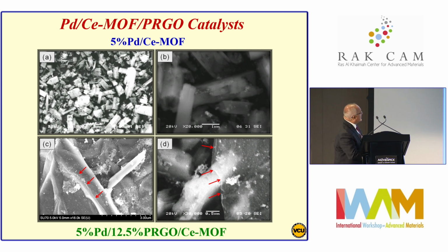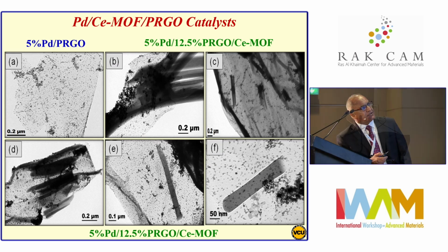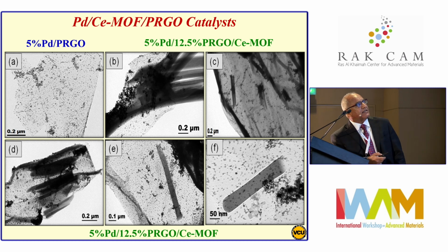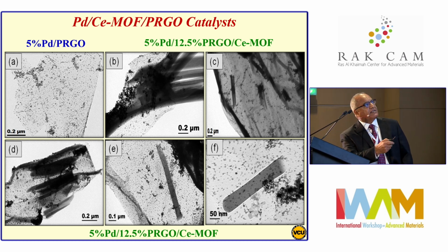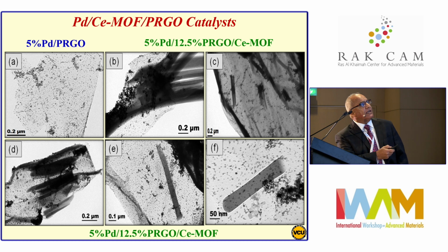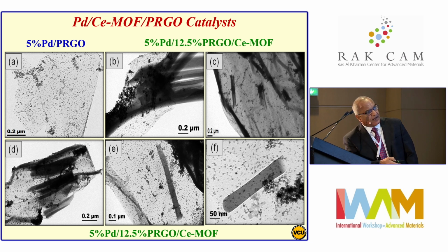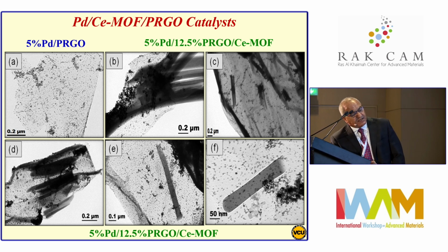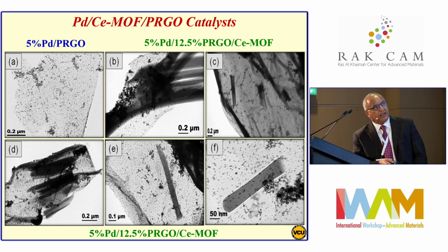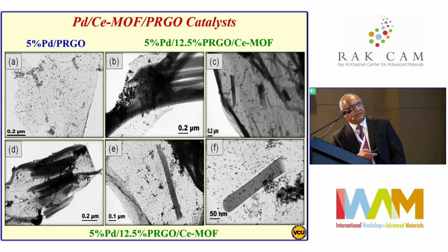Now we look at the reaction, and this is also more TEM characterization, showing the difference: if you have only graphene oxide or reduced graphene oxide, you have palladium nanoparticles distributed around. And if you have the hybrid structure, you still have the graphene oxide in the background, and you see also the crystals of the cerium-MOF, both of them containing two different types of palladium nanoparticles.